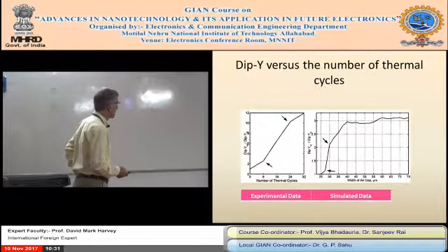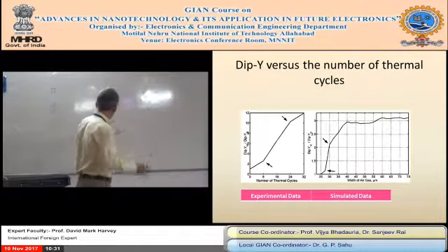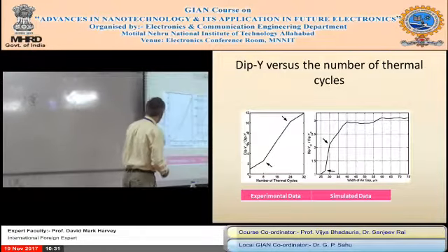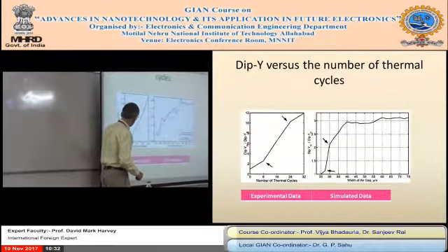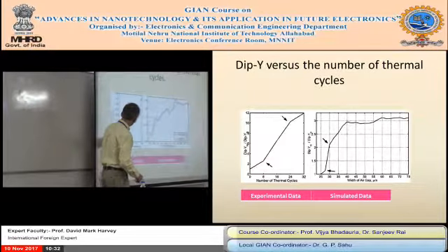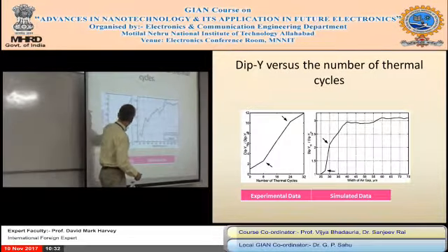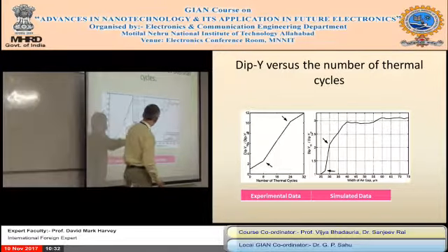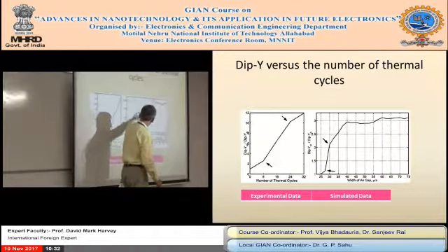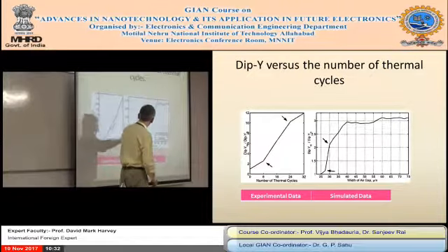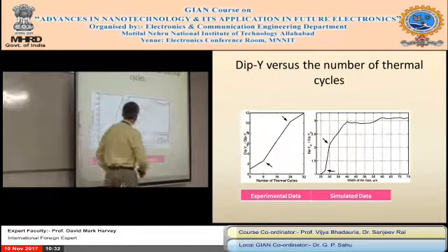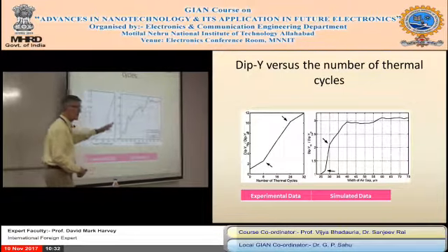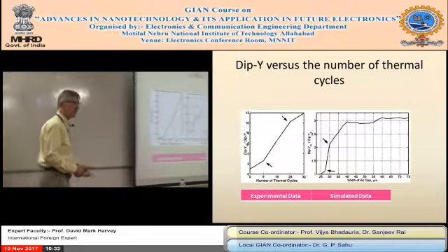So the Dip-Y, which is the size of this central point, again, this is on the real experimental data, from 8 cycles up to about 24 and 32 with a large rise, which meant the cap's growing. And on the simulated data, it's a bit noisy, so he's drawn the best fit on the curve. But you can see it's going in more. So for the first study, it's pretty good.